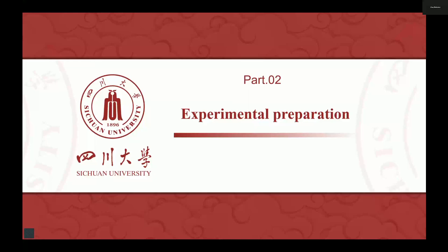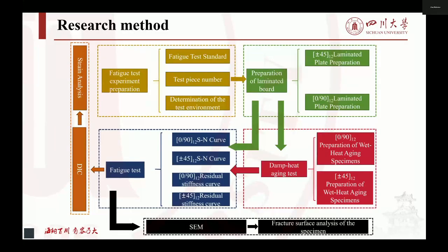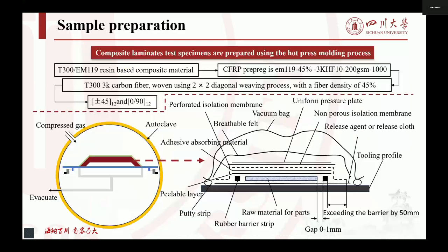Next comes the experimental part, starting with experimental preparation. This project primarily utilized DIC technology and SEM technology to investigate the fatigue life and mechanical properties of CFRP laminates from two perspectives, before and after hygrothermal aging. The laminated panel specimens were fabricated using T300 3K carbon fiber and T300EM119 resin based composite materials through an autoclave molding process.